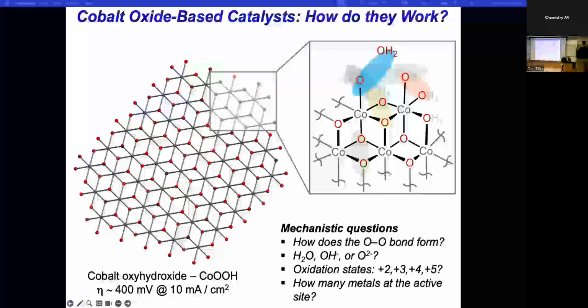One of the metals that we began to look at, and a number of other groups did as well, is cobalt. And that's because cobalt is relatively abundant, not as abundant as manganese or iron maybe, but it's a first row metal. And it's known that cobalt oxides are electrocatalysts for this water splitting reaction at relatively high overpotential. But our approach to this problem was to try to understand how cobalt oxide does this. And if we could understand the mechanism of how water is split on this cobalt oxide, then maybe we could transfer those concepts to catalyst design of a better synthesized catalyst.